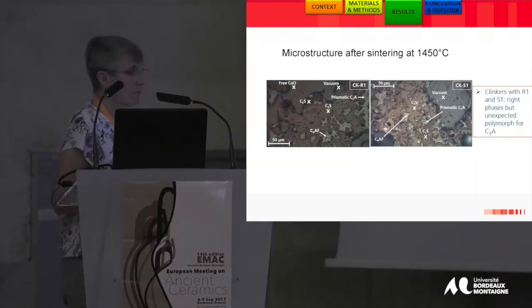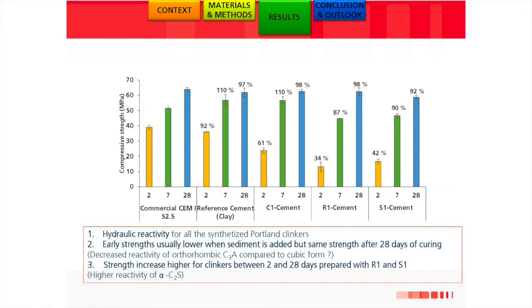On this micrograph, we wanted to check if the microstructure after sintering was similar to what is found in Portland cements. And in fact, with the R1 and S1 sediments, we find the phases typical of cement: calcium silicates, calcium aluminate. Maybe there are some unexpected polymorphs because of additives or minor elements which can change the polymorphs of the calcium aluminate phases.